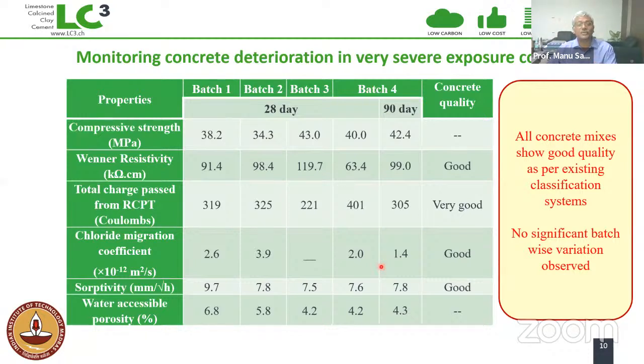And this is actually an earlier 35 megapascal grade concrete. You can see it's about 42 MPa at 90 days. So it's a 30 to 35 megapascal grade concrete, and we are able to produce such low chloride migration coefficients. That clearly tells you the excellent performance one can expect from concrete made with LC3. And even sorptivity and water porosity are in a good to very good range.